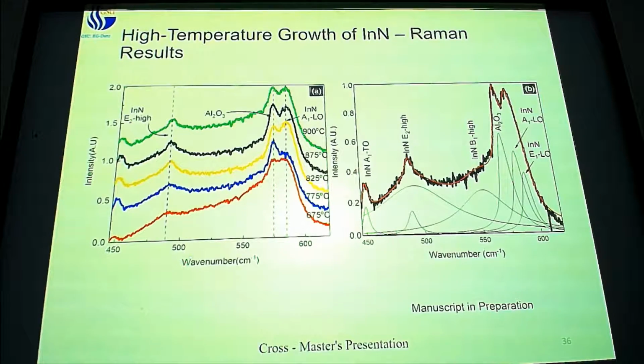But what that means is that we have indium nitride peaks showing up in our Raman system. So we have indium nitride on our surface. We model these indium nitride peaks, and we can correlate them to the phonon structure of the indium nitride. We have the A1 TO phonon, we have the E2 phonon here, and we actually have two peaks for the E2 phonon. There's the B1 phonon here, there's an A1 and an E1 LO phonon over here, so the longitudinal phonons. So this shows us that we have indium nitride all the way from 675 to 900 degrees Celsius on our growth surface.